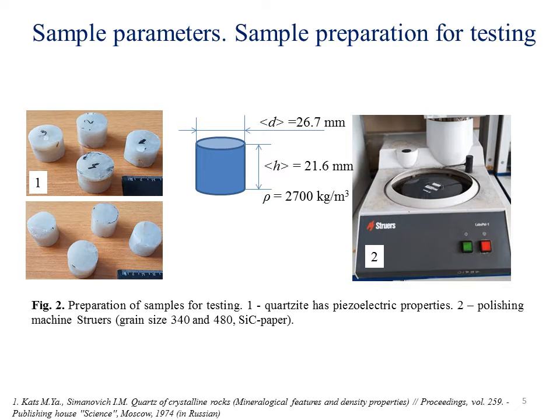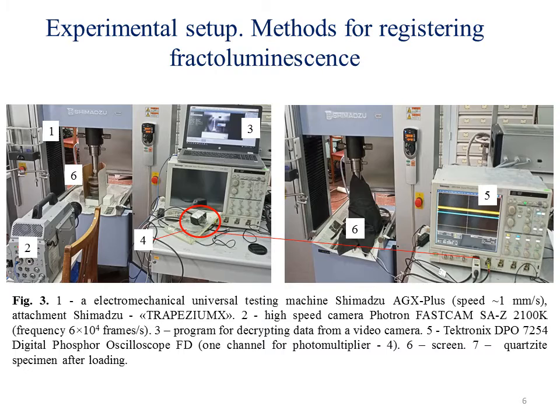For testing, a rock, quartzite, containing quartz, which has piezoelectric properties, was selected. The parameters of quartzite are presented on the slide. The bases of the samples were polished on multi-abrasive silicon carbide paper in water to shine. Tests of specimens were carried out on an electromechanical universal testing machine performing uniaxial quasi-static compression and on the Hopkinson-Kolsky bars installation that fulfills the conditions of dynamic loading.